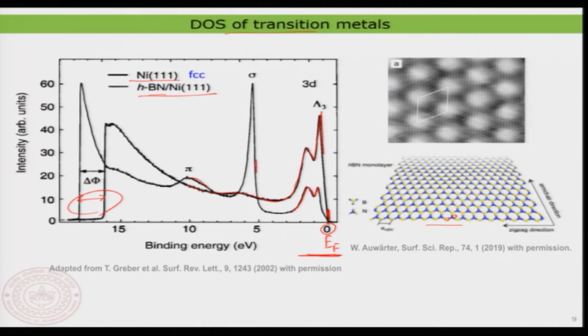So nice, this is good. You also have here an STM image just to show you how the microscopic structure of the boron nitride looks like. You can clearly see the moiré pattern that you are seeing, but inside you can see tiny bright dots which also look like hexagons. That is clearly originating from the boron nitride mesh itself. So these big ones are nothing but the moiré pattern. That's good. So you can deposit the material, do the scanning tunneling microscopy and understand their microscopic structure. You can also do the ultraviolet photoelectron spectroscopy and understand the electronic property of the valence band. Now we are making things more collective, and understanding things in a more consolidated way.